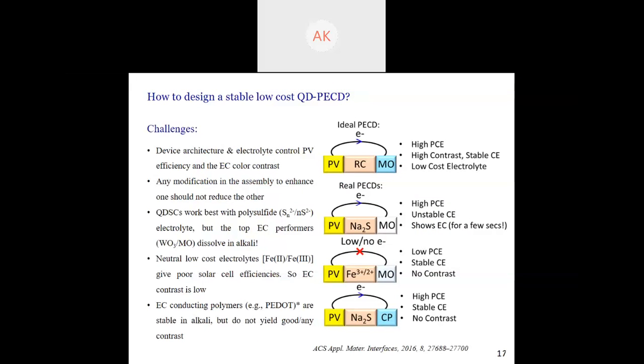So how do we design a stable, low-cost quantum dot PECD? In an ideal PECD, the device structure and the electrolyte should be such that the photovoltaic efficiency is high and the electrochromic color contrast is also high. The transition metal oxide, or the MO, as I've shown in the blue box here, should be stable in the redox couple electrolyte, and the redox couple electrolyte should also be low cost. That is an ideal PECD. But in reality, it is not the same. Any modification to this assembly will enhance one and simultaneously reduce the other.